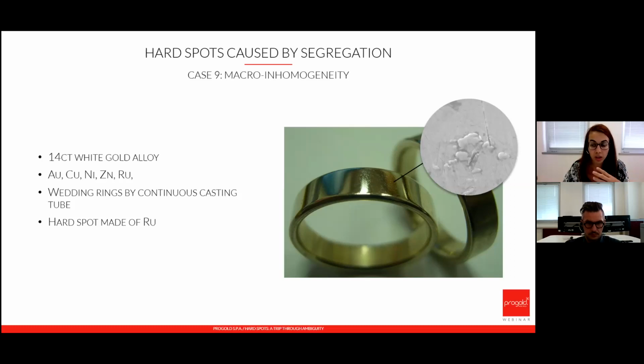So here, if we are not careful, we're going to have segregation of elements, and in some parts we're going to have a composition that is different from the composition of the other part. This is why we usually recommend that you do a pre-melting before using continuous casting, and even if you do a pre-melting, you try to keep mixing the melt while you're doing this particular process. In this case, we have hard spots made out of ruthenium.